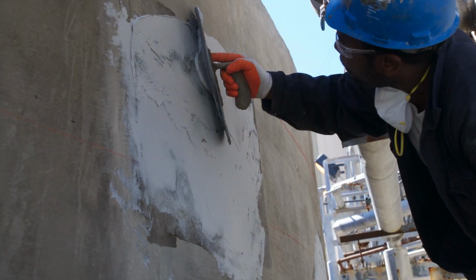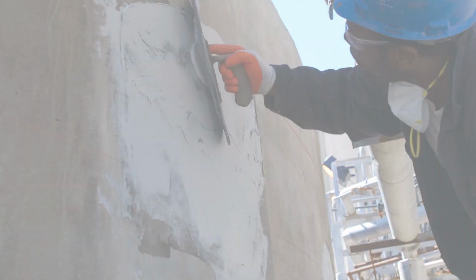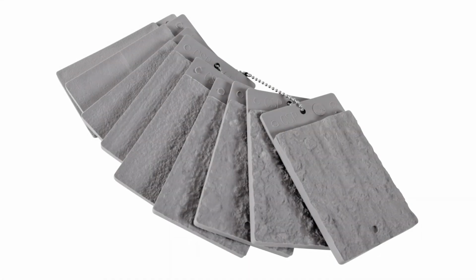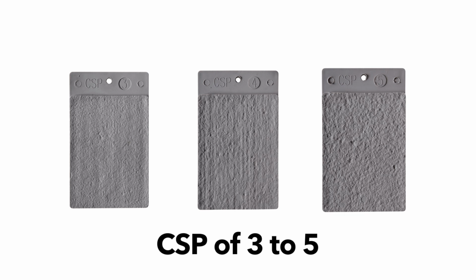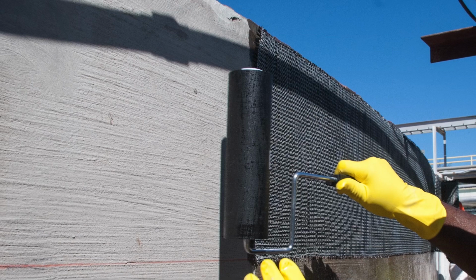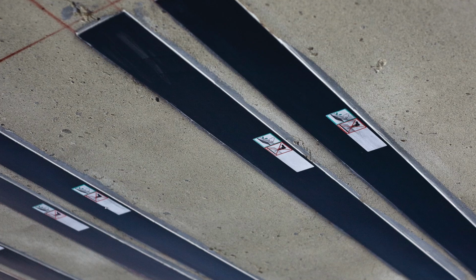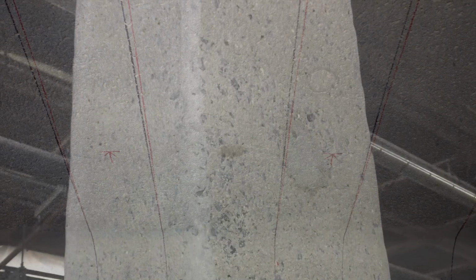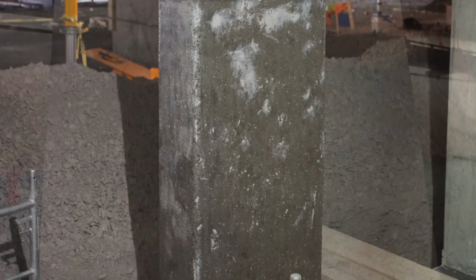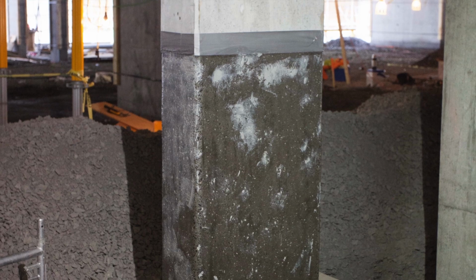Surface preparation is dependent on the type of FRP material specified. Regardless of the application, a CSP of 3 to 5 is generally required in the project specifications. A CSP of 3 to 4 is generally used for fabrics, and a CSP of 4 to 5 is used for laminates. Grinding may be necessary for treating all protrusions and form lines, as well as for rounding off outside corners to a radius of ½ inch or 12 millimeters if they are covered by FRP. This will avoid damage to the FRP fibers and provide an even contact between the substrate and the FRP.